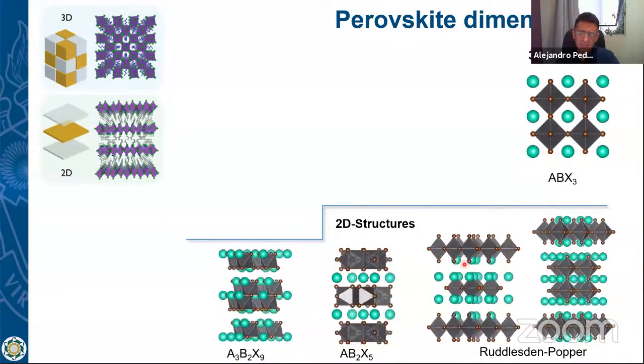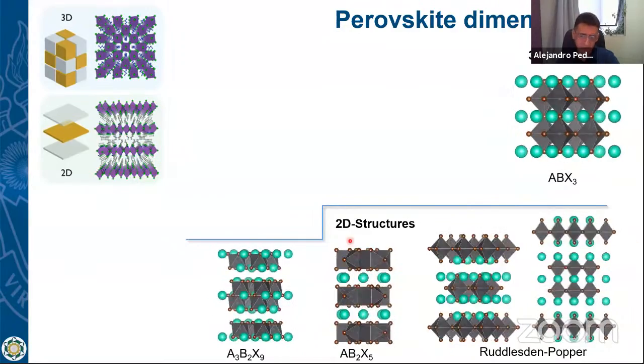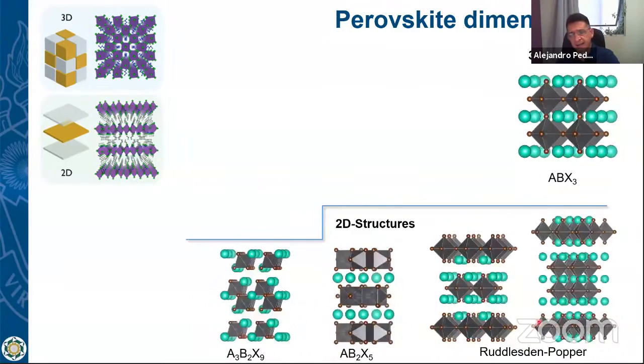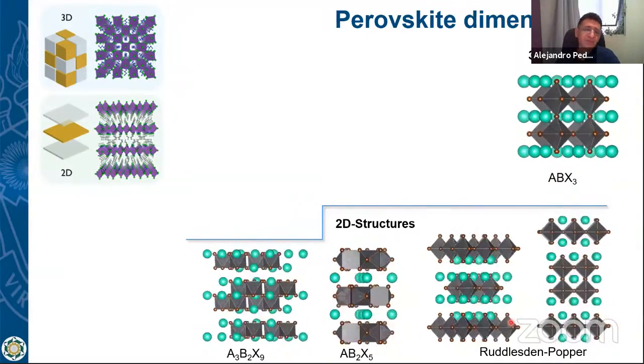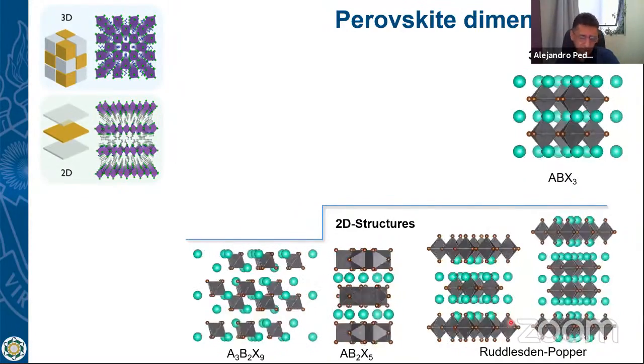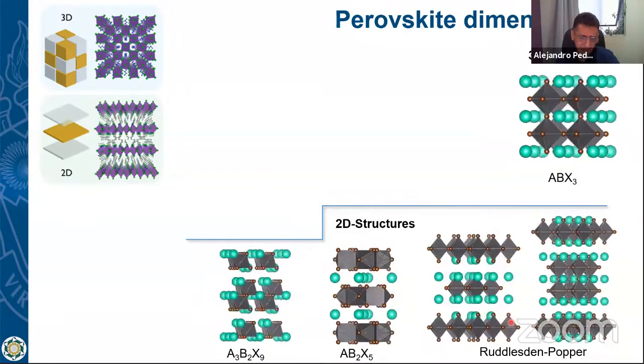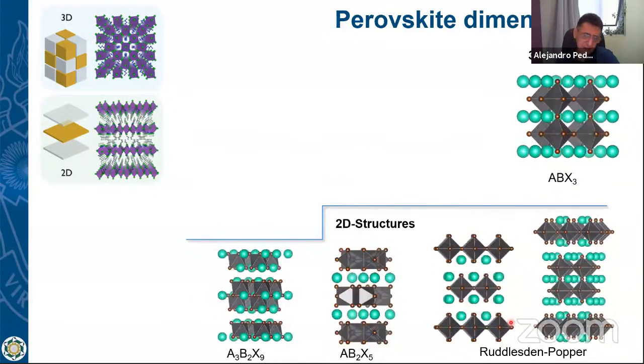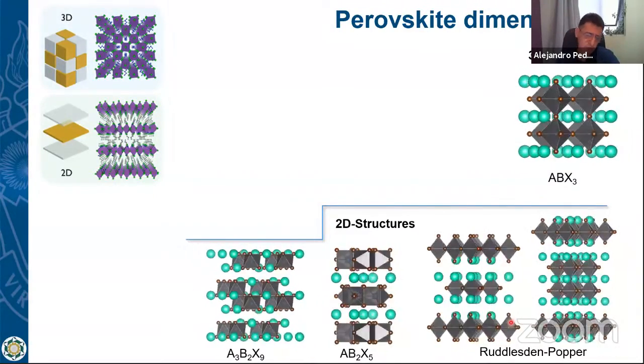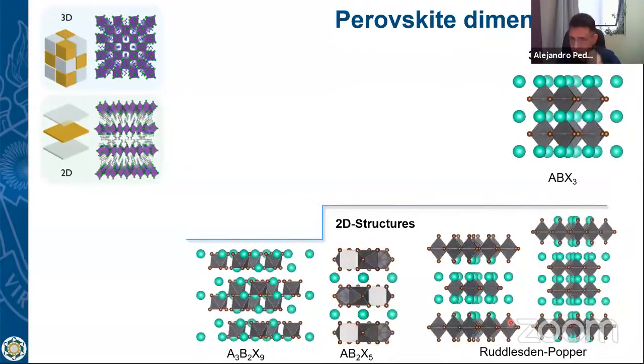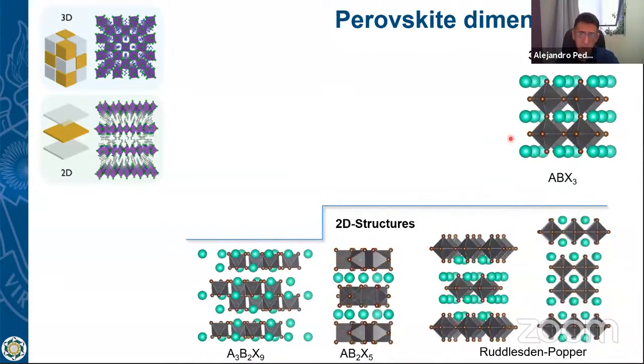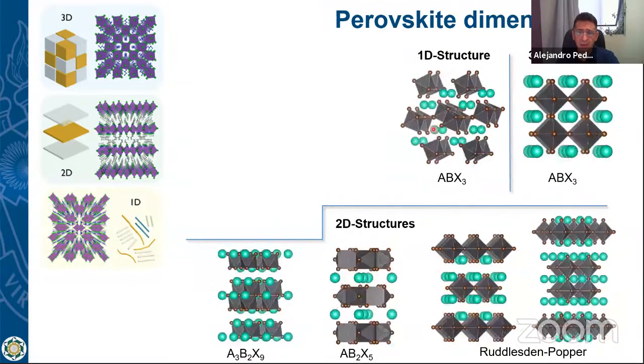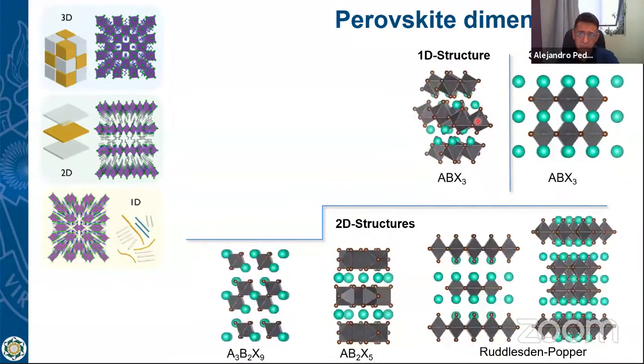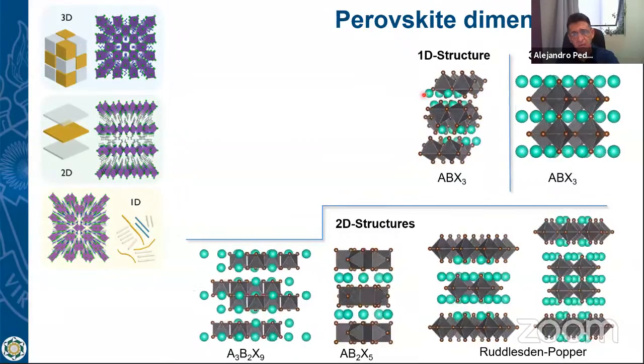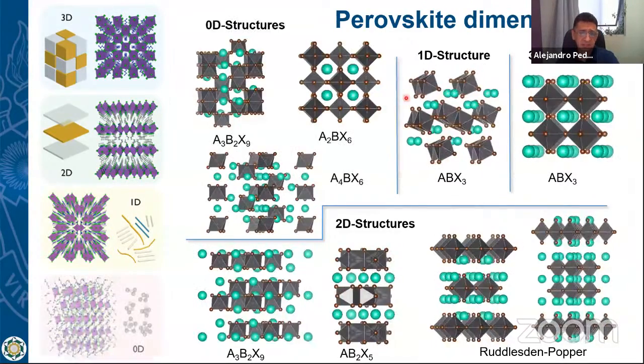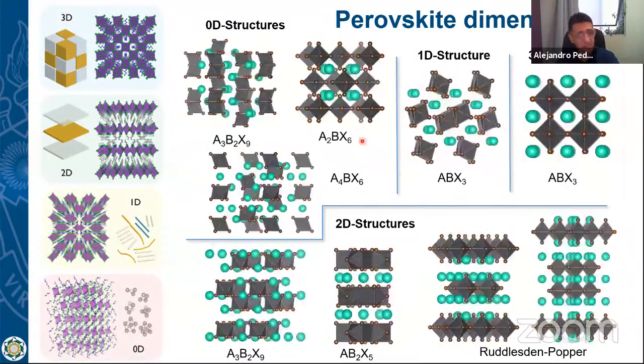Be careful with that because these are not perovskites anymore. They are perovskite related, but usually people call them 2D perovskite, but this is not a correct description of the compound, but you will see things like that in all the literature. When the octahedra form columns, we have a 1D. When the octahedra are isolated, we have a 0D.